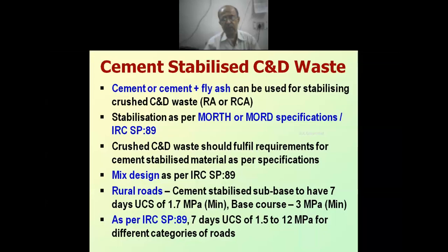For rural roads, cement stabilized subbase is to have a 7-day UCS of 1.7 MPa, and base course is to have 3 MPa strength. As per IRC SP 89, 7-day UCS ranges from 1.5 to 12 MPa for higher category roads. SP 89 says some base layer must have a minimum strength of 1.5 MPa. For rural roads, we have 1.7 MPa, so definitely 1.7 MPa we can take, 7 days stabilized material strength. For base course, normally for rural roads, it is specified as 3 MPa strength, 7 days.